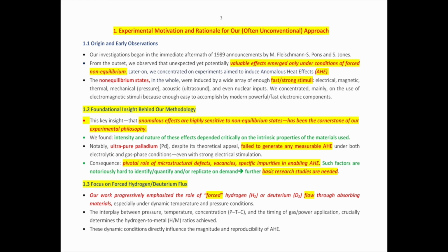Moreover, in the beginning, we thought that with a very high purity material, ultra-pure palladium, 99.9995, we would get a really optimal result. But we found zero. It means with ultra-pure material, nothing happens. So you need some impurity or some dislocation or something strange.